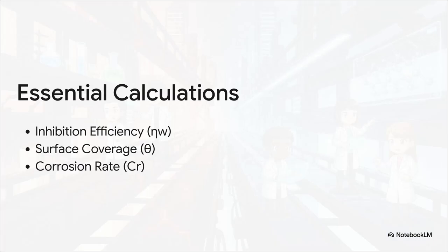Once you have those weights, that's when the real analysis begins. Researchers use these numbers to calculate the corrosion rate. But even more importantly, if they're testing a chemical inhibitor, something designed to actually stop the rust, they calculate the surface coverage and the inhibition efficiency. For example, in one particular study, by adding just 400 milligrams per liter of an organic inhibitor to a highly acidic environment, researchers were able to prove an 89.5% inhibition efficiency. These calculations are absolutely crucial because they're the ultimate proof of whether a defense mechanism is actually working.